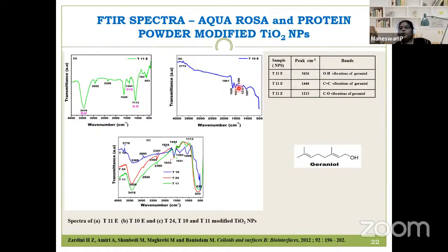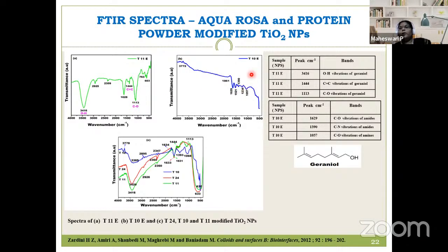And similarly, in the case of protein powder, it is a combination of amides and amines. So we can see here 1629, it has a CO vibration of amides, and at 1390 we have the CN vibrations of amides, and also at 1057 we have the CO stretching vibration of amines. Now these are going to play a major role when it is modified with TiO2 nanoparticles. So this is the one which we have seen here.